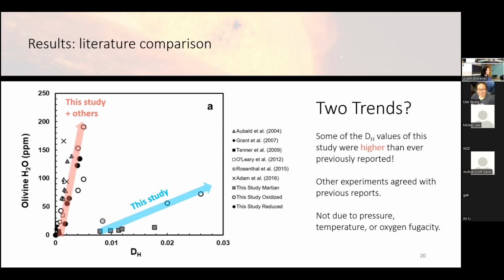This is where things get a little bit interesting. Up until this point, it seemed to be that everything was falling on one linear correlation. But my work didn't. It's a bit out there. And I've already looked at pressure and I've looked at temperature, and they don't seem to be what's making it do this. It also doesn't seem to clearly follow oxygen fugacity in that some of the reduced experiments are on there. So that isn't the deciding factor, which really only leaves composition.